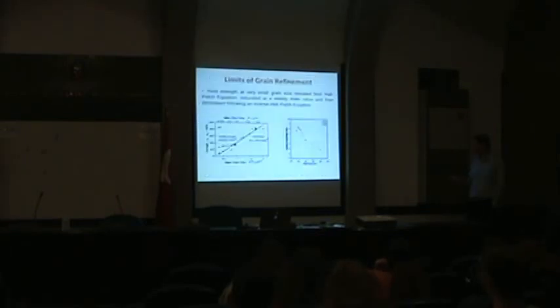There you go. Grain boundaries do act as a source, and grain boundaries do act as a sink. So since you increase the number of grain boundaries, since you make the grains so small, dislocations and grain boundary interactions do change. So that gives the inverse Hall-Petch. But, to be honest, no one works with a 10 nanometer grain material. So what they usually do is operate somewhere in here. 100 nanometers is fine for these guys for mechanical applications. So you don't want to tip over the peak, so you have to work somewhere in here. And that's what people do anyhow.